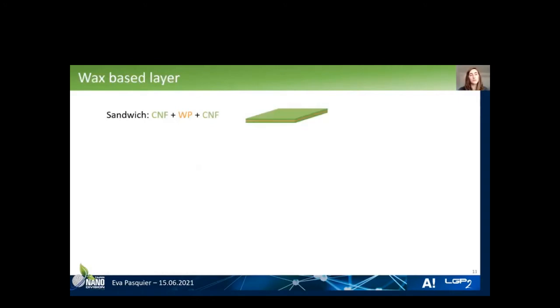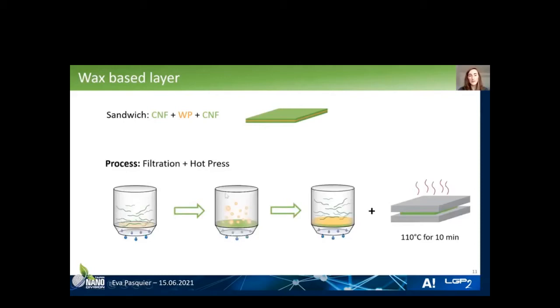Then we engineered the wax layer. For that, we used a sandwich method. It consists of first filtration of the nanofibers. Then we filtrated the wax particles, and at the end we filtrated again some nanofibers on top. So we have the wax in between two layers of CNF. And at the end we used a hot press so that we dry the film and also partially melt the wax particles so that it would make a continuous layer of wax.